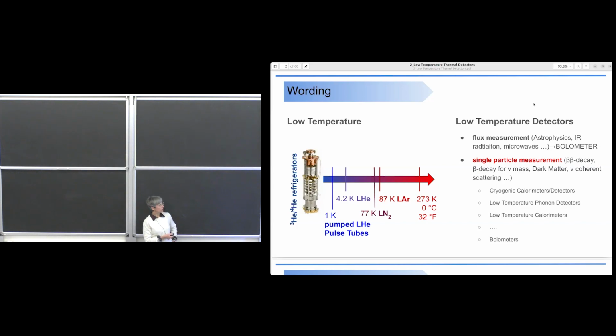If we want to go below, we can pump the helium gas over the liquid, and in that way we can achieve 1 Kelvin. And in more recent years, there are technologies that allow you to achieve this temperature without using liquids. This is very useful, especially if you have safety issues. And the technology is that of pulse tubes. So with pulse tubes, you can achieve a very high cooling power down to a temperature of about 1 Kelvin.